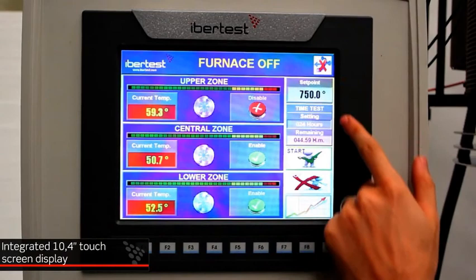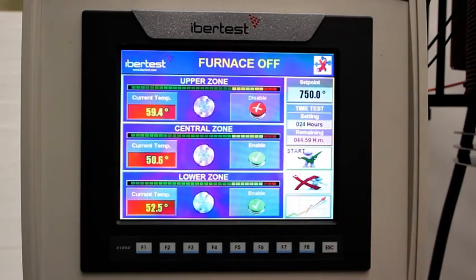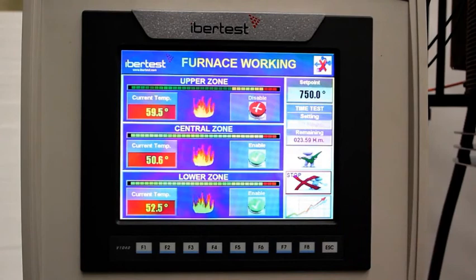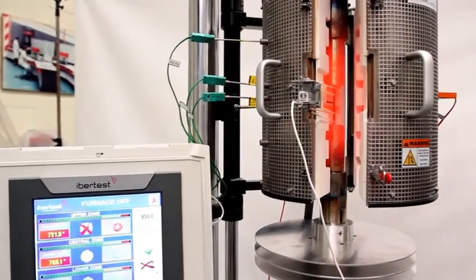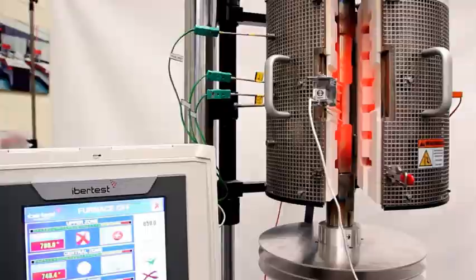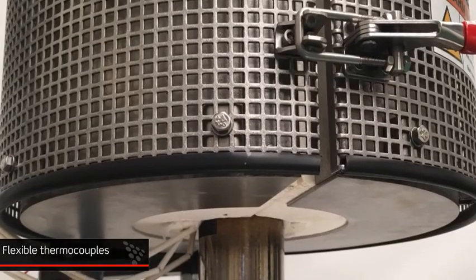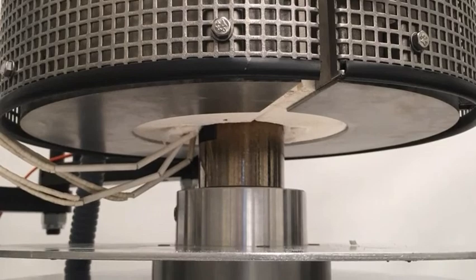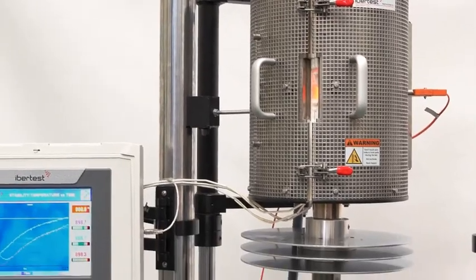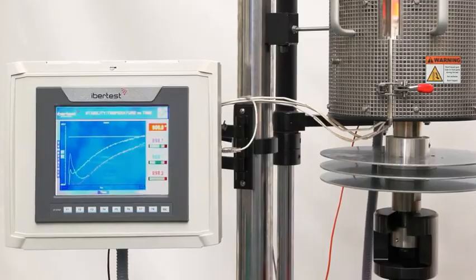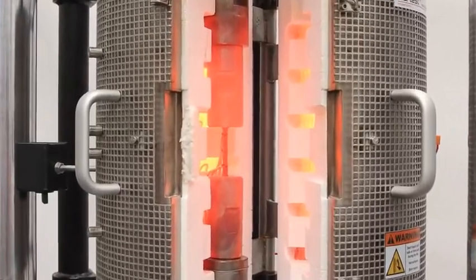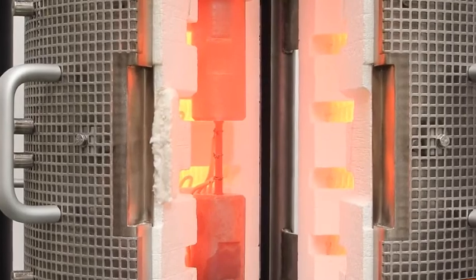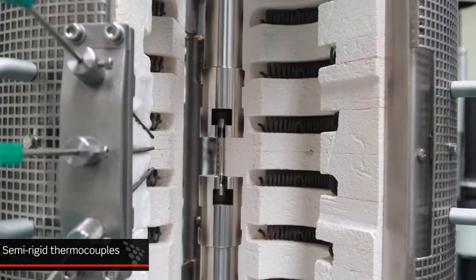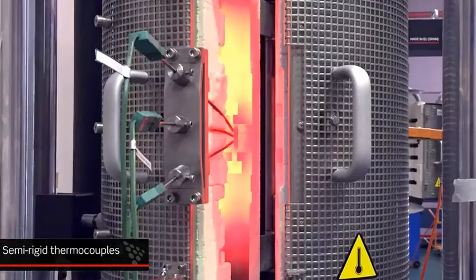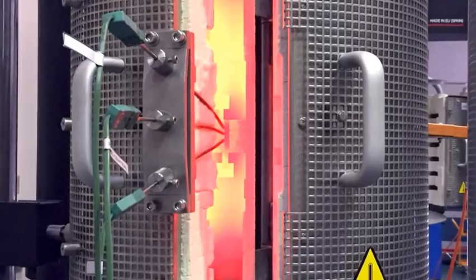So here in the furnace, you set the temperature 750 degrees Celsius, and you start the furnace, and with the symbol of burning, you see that the furnace is hot. You also see the actuator, the adapter, and the specimen red, and then these are the thermocouples, which have ceramic tubes around them for protection from the temperature, and that's how it goes inside. And you see the adapter and sample, and three thermocouples attached at the top, bottom and center are all red because of the high temperature. You don't perform the test like this. In this video, it is just shown to you by opening the furnace how hot it is at 750 degrees Celsius.